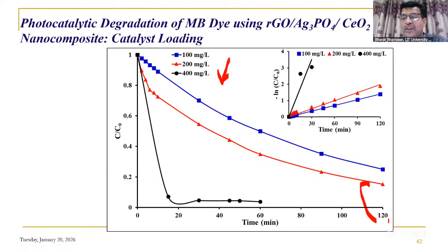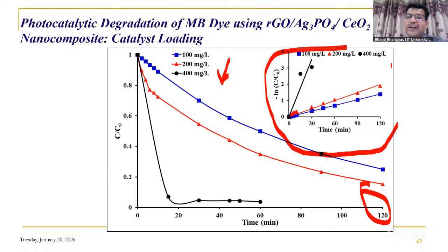After 120 minutes, at 100 mg per liter, almost more than 70% degradation is observed. But at 400 mg per liter, almost more than 95% conversion was observed, and it is well fitted by first order kinetics.